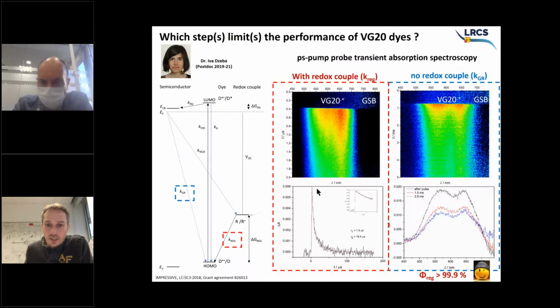So typically from this, you can deduce the speed of this hole transfer to the redox mediator. We have two components, which we attribute to the monomer and the aggregates. One is 1 microsecond, the other one is 20 microseconds. And if you want to measure the geminate recombination, which is the unwanted process, then you use exactly the same procedure and techniques, except that you remove the redox couple to block this reaction. If you look carefully at the scale, you go from a few microseconds to a few milliseconds. And this is the geminate recombination process, which takes a couple of milliseconds.